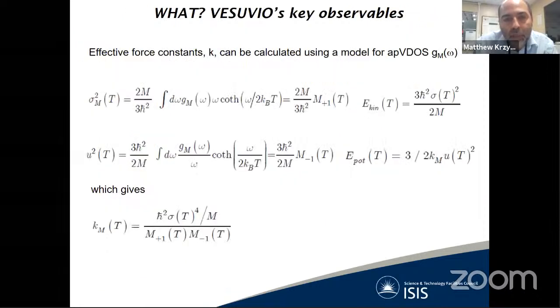And this can also be done not only from experiment, but can be modeled. If you have a good model of your atom-projected vibrational densities of states, you can use the combination of the expression giving us the variance of the momentum distribution and the root mean square displacement of the nucleus through the atom-projected vibrational densities of states, together with the virial theorem for the harmonic oscillator, to come up with an expression for the magnitude of the effective force constant that can be simulated based on the results for your vibrational density of states and contrasted with the results from experiment.